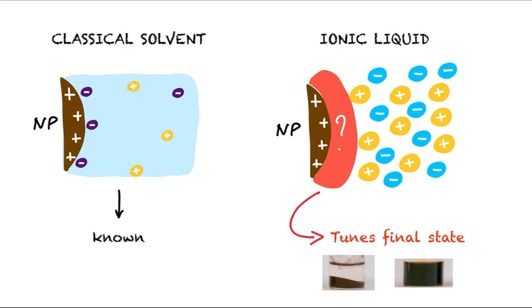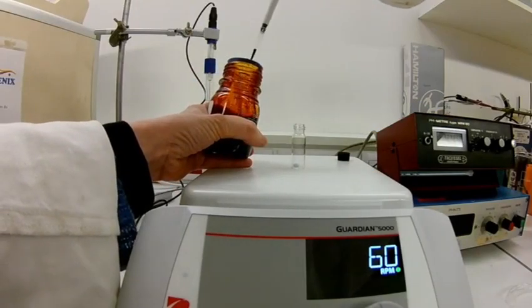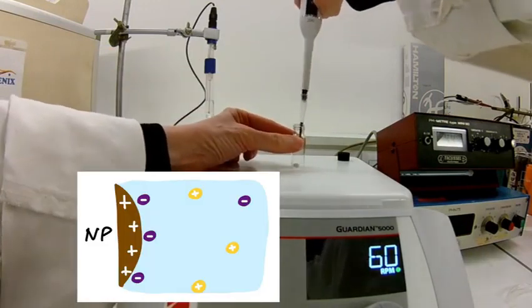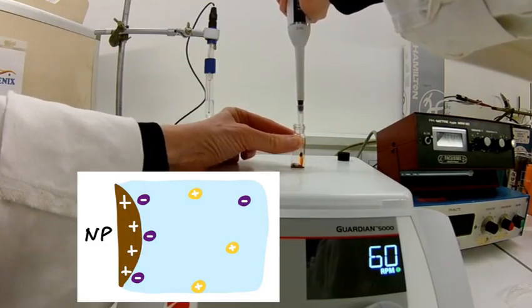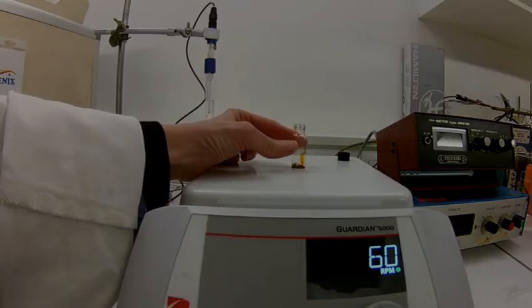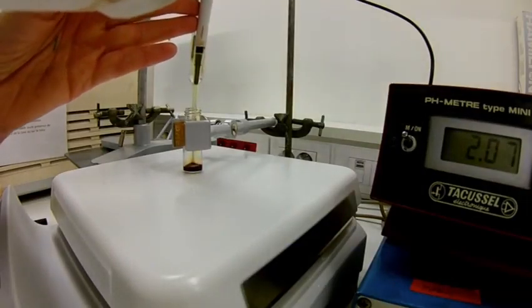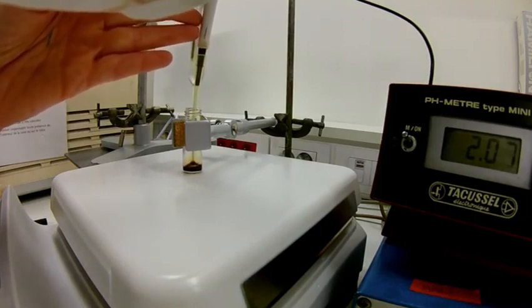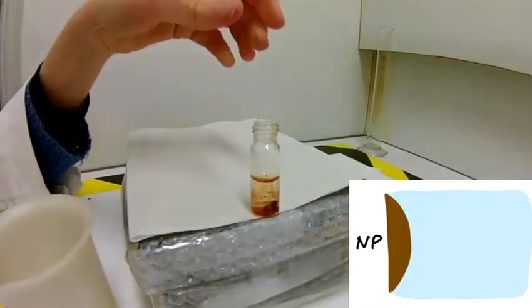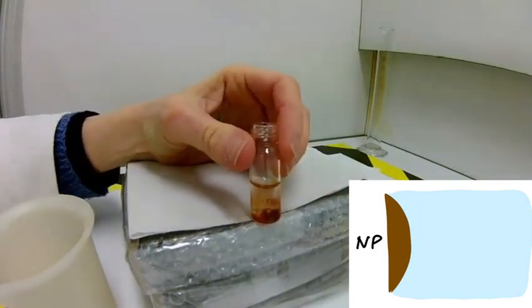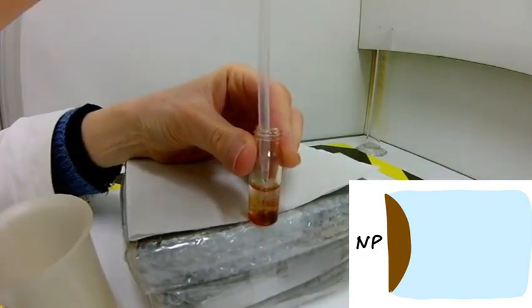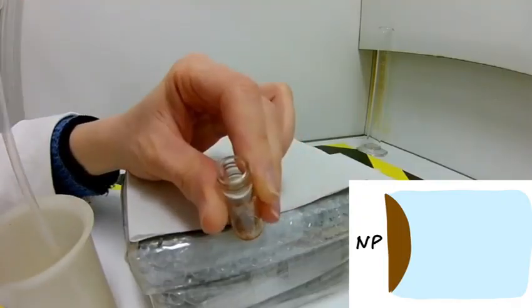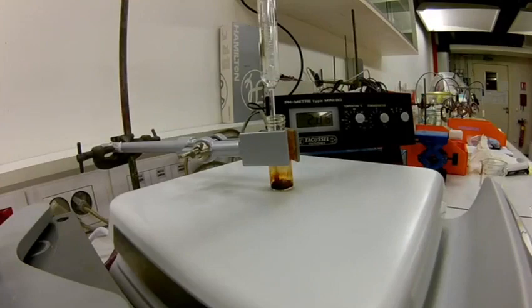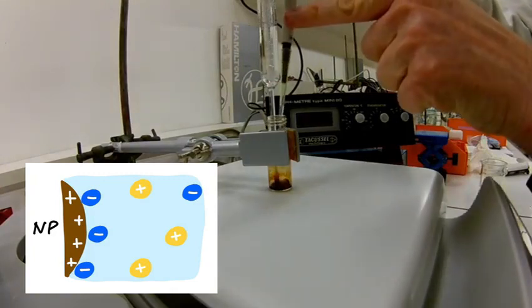We illustrate the process to produce the samples with a short sequence on a small test sample. We begin with the dispersion in water, where the particles have been synthesized. They are charged, and the counterions are here the purple ones. The first step is to remove the charge from the particles in order to remove the initial ions so that they can be washed by several steps, removing the liquid that you see above the particles, however never drying them. After several of these washing steps, we can introduce a new charge on the particles and the desired species, here the blue counterions for example.